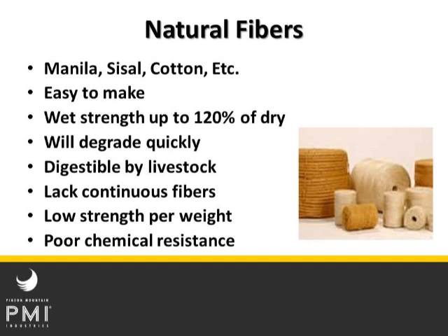Big problem with them is that they aren't continuous fibers, and depending on the quality of the plant, you can have a very, very long fiber or a very short fiber, long being a foot or two versus short being a few inches. And obviously the more the fibers are intertwined, the more strength you get out of it.